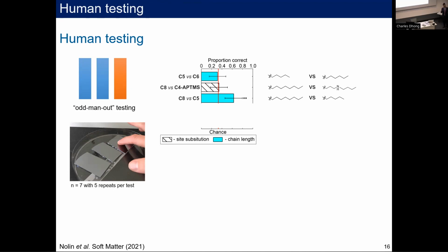So again, these are on top of silicon wafers. They aren't that physically different. It's just really that surface chemistry that's different. And so if we do this and we change the terminal carbon for a nitrogen group, we also see that people can tell this apart. And if we include this effect of increased chain length and this carbon for nitrogen substitution, people can tell this apart with the greatest accuracy.